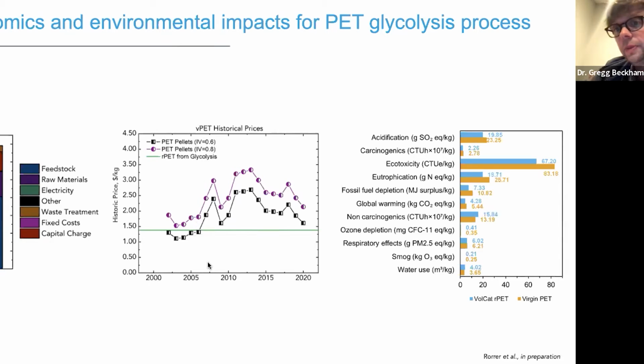From a life cycle assessment perspective, now looking at virgin PET again in orange and this rPET from this volatile catalyst process or glycolysis process shown in blue, you can see that we still have some work to do, right? And so if you look at fossil fuel depletion, it is a reduction. So you want, in this case, blue to be smaller than orange. It is, but not by much. And we still have work to do to reduce the energy intensity.